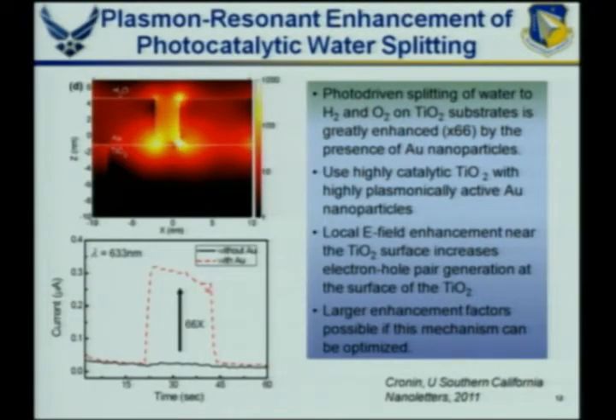If you look at electrodynamic calculations of where the fields are in these types of systems, they're often at the junctions or gaps between metal particles, or here in this case at the gold TiO2 interface. So you have large fields over here that are driving this. This is, as I mentioned, a very unoptimized system. If you can try to optimize this, take advantage of those fields, hopefully you can get much larger yields for the benefits of using plasmons to enhance this chemistry.